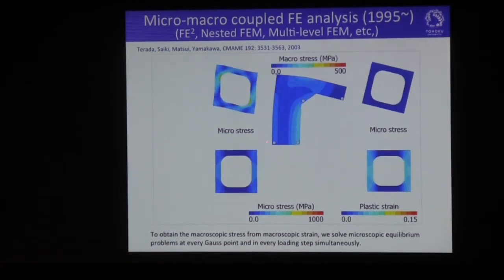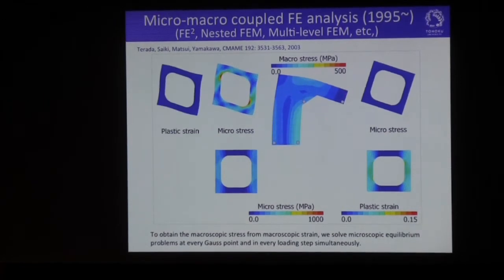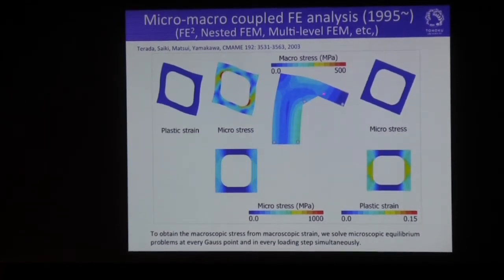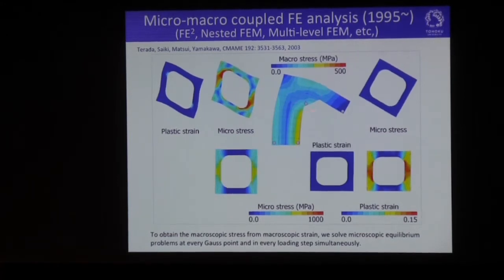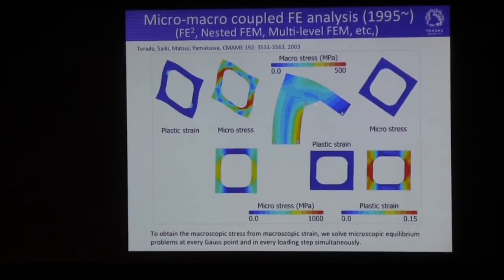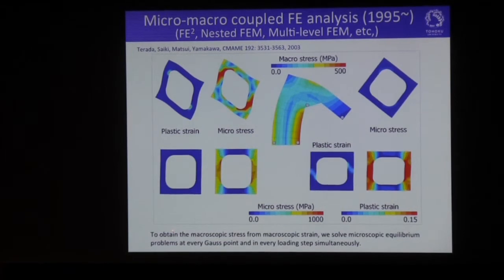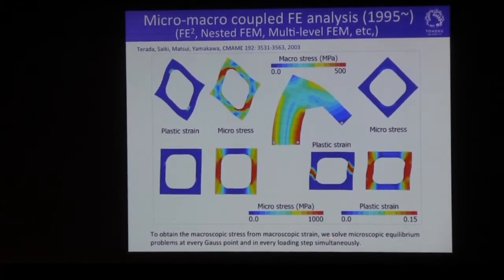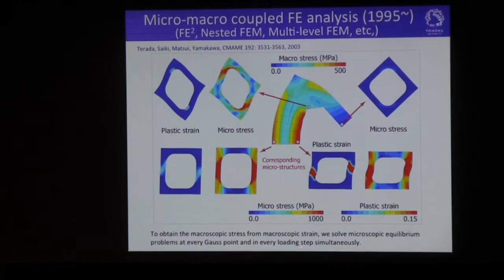Here is my macrostructure. We solve the equilibrium problem of this macrostructure without any macroscopic constitutive equation. Instead, in order to obtain the macroscopic stress in this field from the macroscopic strain, we solve the microscopic equilibrium problems at every Gauss point and in every loading step simultaneously.